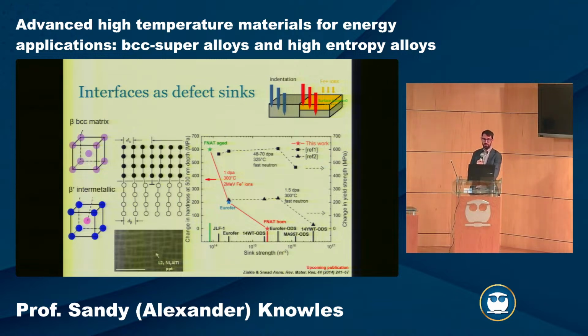What we can do, by creating this nanostructure in a ferritic superalloy, is get to the same level of fine-scale microstructures that we see in these oxide dispersion strengthened materials. And if we can get to those very fine-scale microstructures, then when we irradiate the material, we see no apparent irradiation hardening.